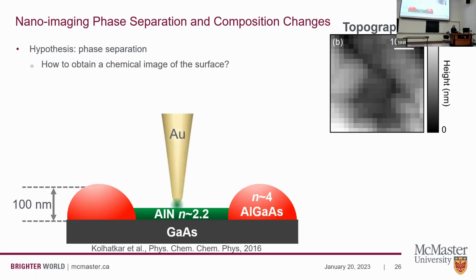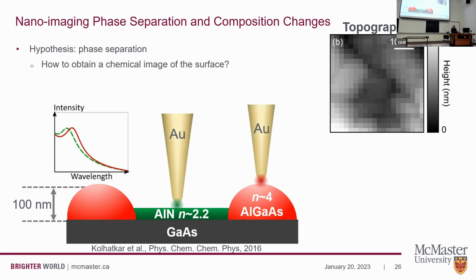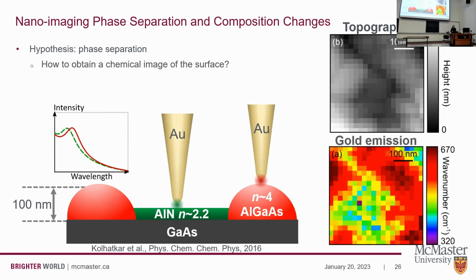Therefore, if we image the gold emission in a pit and on an island, we should expect to see a shift in the gold emission. This is what we obtained. So here is an image of the position of the gold signal as a function of the position on the surface, which was taken simultaneously with the topography.